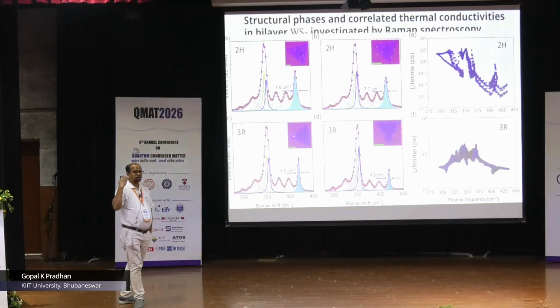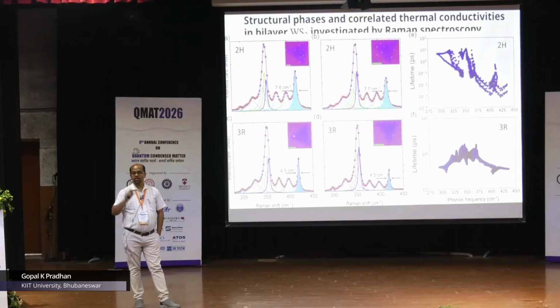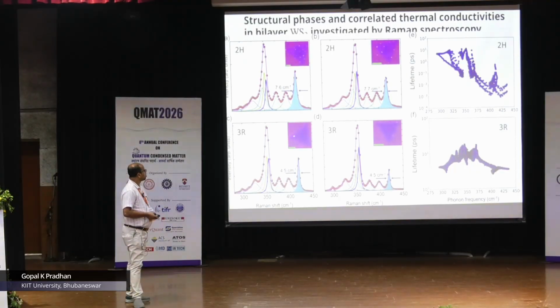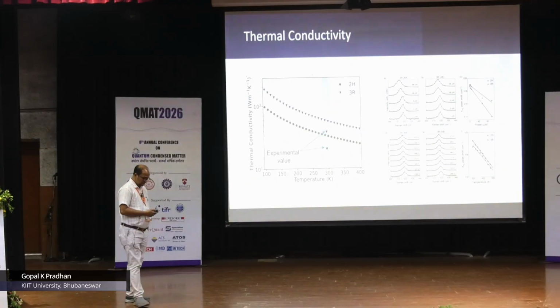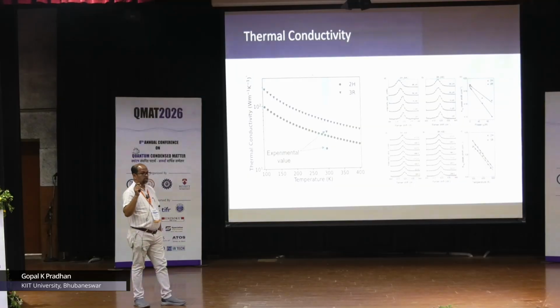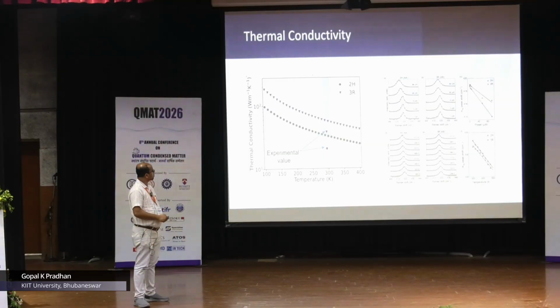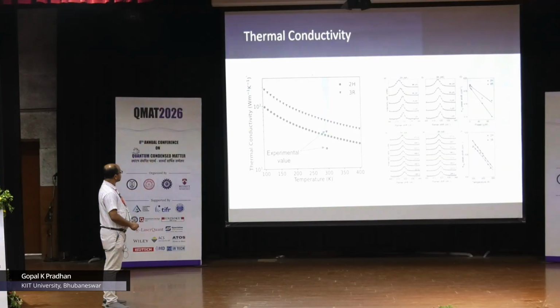Now, if you remember the thermal conductivity expression, the lifetime is a parameter: one third C V squared tau. So naturally the thermal conductivities are supposed to be different, and one can do similar modeling of the heat transport and find out what the thermal conductivity would be. And as I told you in the formula, you have two parameters, one is d omega by dP, the laser power coefficient of the Raman shift, and the other is the temperature coefficient, d omega by dT, and that is what you do here. This is for the 2H phase, this is for the 3R phase. One of them is as a function of temperature, the other is as a function of laser power, and you measure d omega by dP and d omega by dT, and that is what is used to calculate the thermal conductivity. And then we see that we have these values at different temperatures.